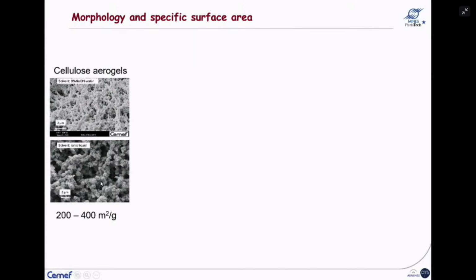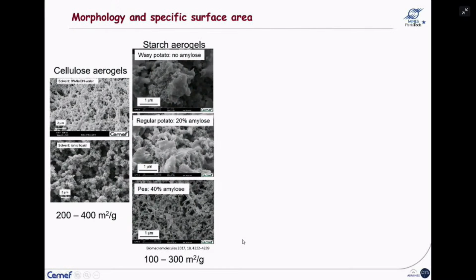And you see there is a difference in morphology. And in all cases, there is a rather high specific surface area of several hundreds of square meters per gram. For starch aerogels, the morphology depends a lot on the type of starch, or better to say, on the ratio of amylose to amylopectin in the starch. So you see for waxy potato or waxy maize, where there is no amylose, there are large pores, and the specific surface area here is low.